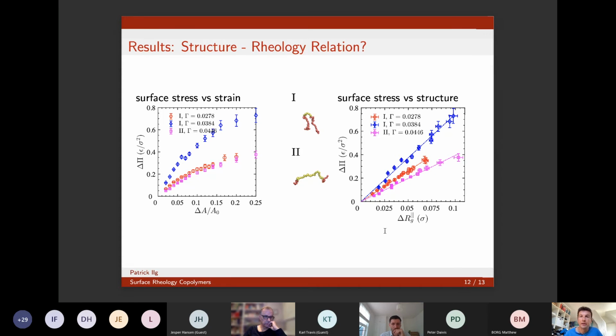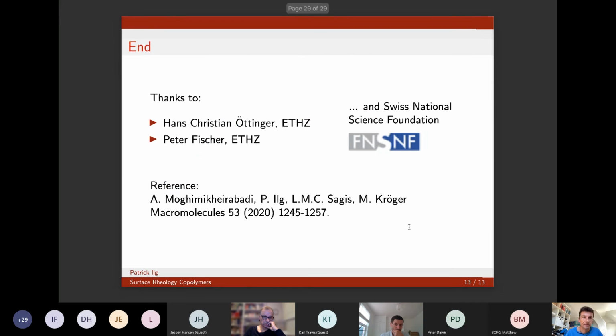And we also measured the change on the right-hand side, the change in the gyration radius, the in-plane component of that. And if we plot them parametrically against each other, we find that they are nicely linearly related, which gives us some hope that maybe a relatively simple constitutive relation can be found for this interfacial rheology business.